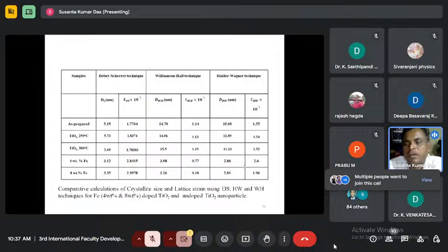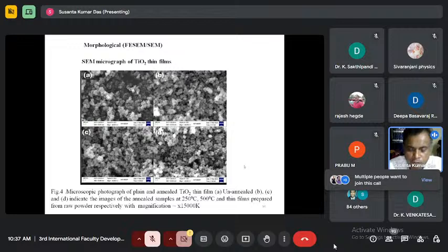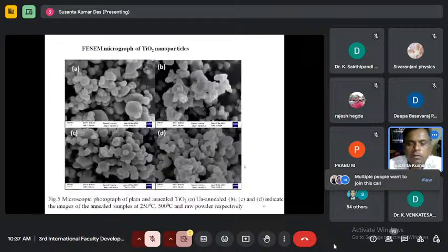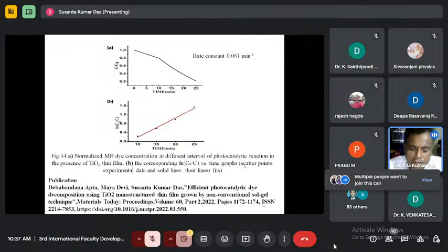these are the routine type of works for all types of material that we have grown, and we went for other conventional studies like FESEM and so on. And we found that those are really coming in the nano dimension. So we converted the micron size into nano size by just adopting this process only. And we did the experiment, and we got that in nano size, that is really showing good result. And the cause is very obvious, because in nano dimension, the surface area is very large. So a large number of dye molecules adsorb there, and they get split by photocatalysis. So that was proved in our case.